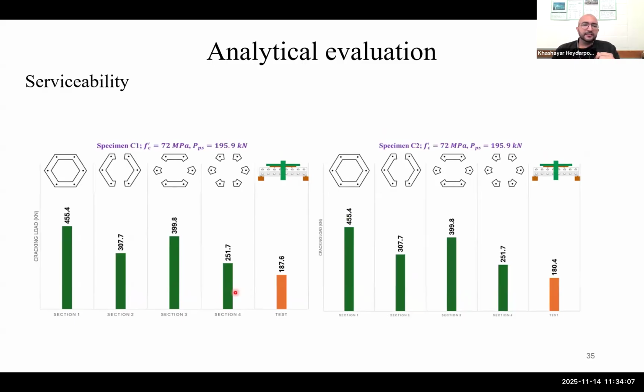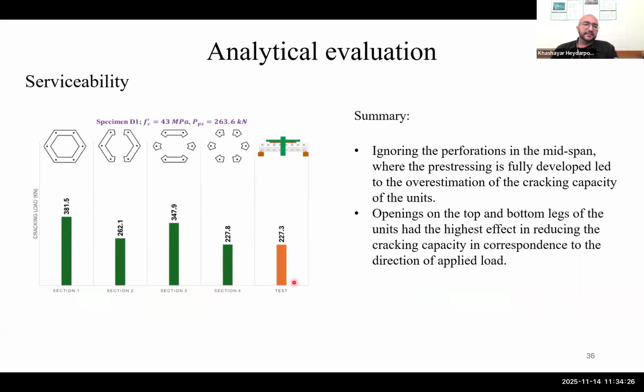The specimens C1 and C2 had the lowest pre-stressing level, and we can see that the pattern remains almost the same, and the analytical formulation was able to get an accurate response. And also for specimen D, we got almost the same value for the analytical evaluation and the test, where we had a lower concrete compressive strength.